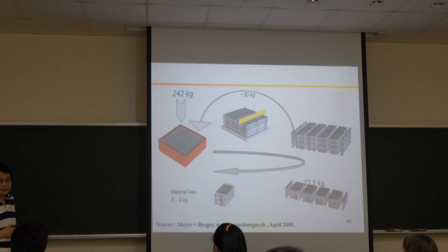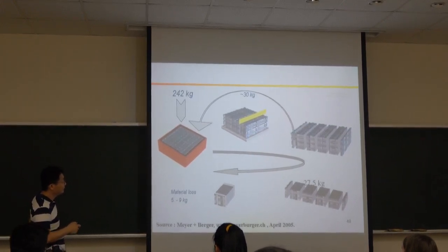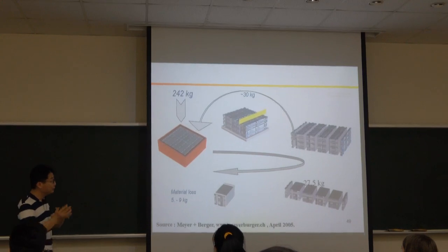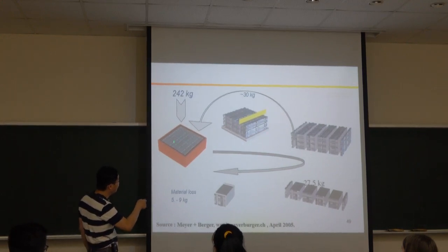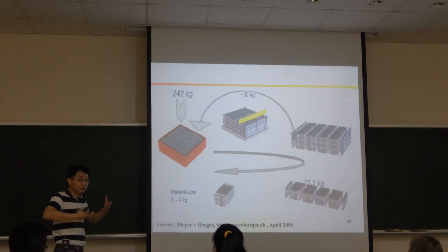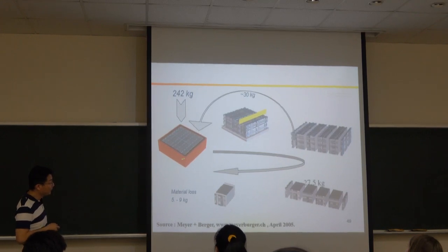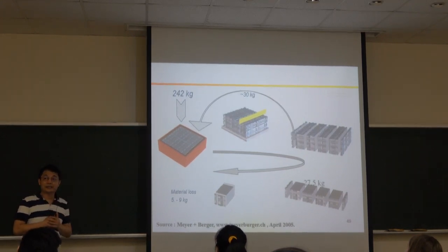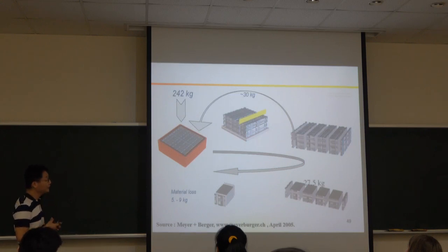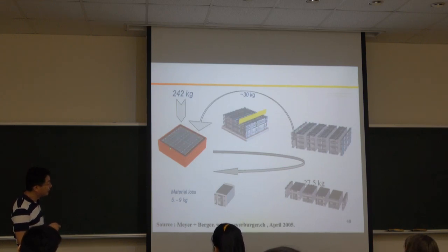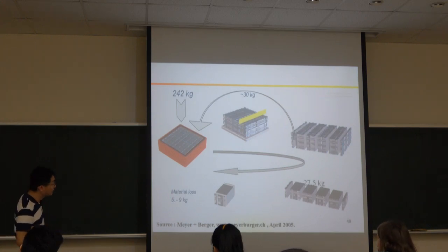Because you have to melt the silicon in the crucible and then increase the temperature, on the surface of the crucible area there are a lot of defects because the solidification rate is different. Therefore, we have to cut the surrounding area, the six planes: the top side, surrounding this circle, and also the bottom side. So the material will be lost.